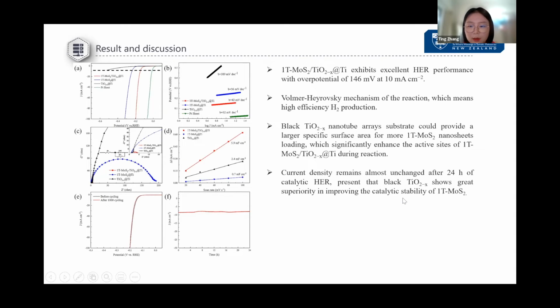We also did the stabilization test, and we found the current density doesn't drop significantly for at least 24 hours, because after 24 hours, we stopped the experiment. From all this experiment and analysis, we make the conclusion that the combination of 1T-MoS2 and the black titanium dioxide can enhance the 1T-MoS2 content, and it also enhances the HER properties of the catalyst.